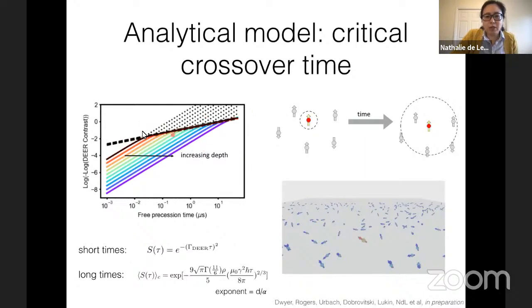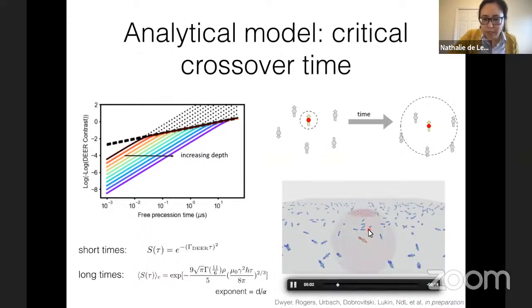The time at which this crossover happens just depends on the depth of the NV center. So there's a nice geometrical interpretation: at very short times, the NV center sees contributions from a lot of distant spins. Then at some critical time, set by the depth of the NV center, it starts to see the surface, and it's strongly coupled to a few spins. Then it starts to see this configurational averaging, so it sees this 2D bath, and you get this exponent of 2/3. I have this video that hopefully plays nicely in Zoom. Basically, think of this as the sphere that encapsulates how many spins the NV center can see in strong coupling. There's some time delay before it hits the surface, and then you start seeing this area law scaling.